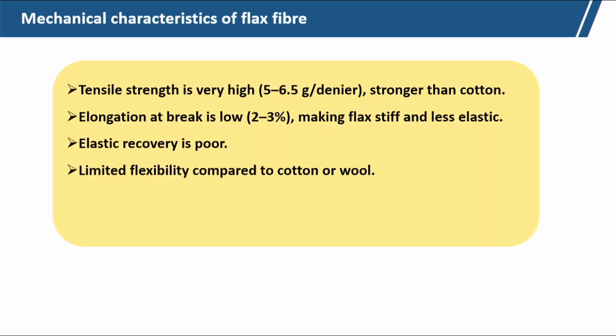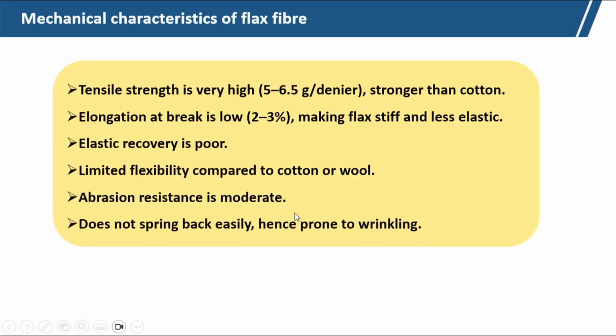So, it gives lower elongation, but the uniqueness is there. It is basically a stronger fiber, and also its thermal conductivity is more. So, it gives a cool touch, and due to the higher Qmax value, Qmax means instantaneous heat absorption, this fabric made from the flax fiber is good for summer wear, and due to the very high tensile strength, this is used for technical applications, different protective applications we can use. Abrasion resistance is moderate and it does not spring back easily because of its lower elastic recovery.